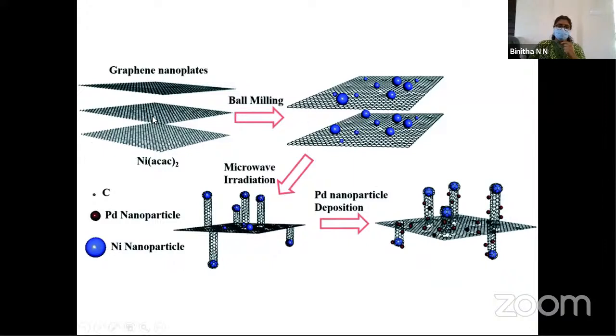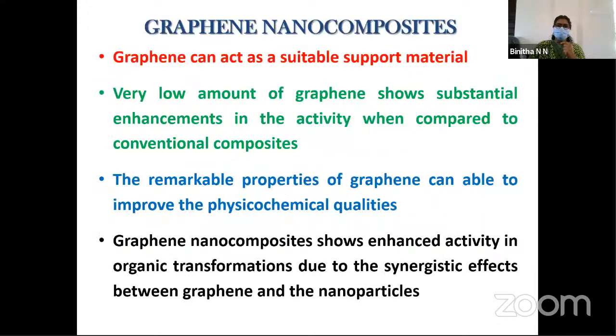Graphene nanoplatelets, not graphite, graphene nanoplatelets. Few layer graphene is ball milled with nickel acetate to form a nanotube decorated nickel deposited graphene sheet, and it is additionally decorated with palladium to form a composite which is a highly active catalyst. So there are lots of possibilities for the incorporation of other materials to graphene and also for the ball mill exfoliation of graphene. And why do we prefer the formation of nanocomposites?